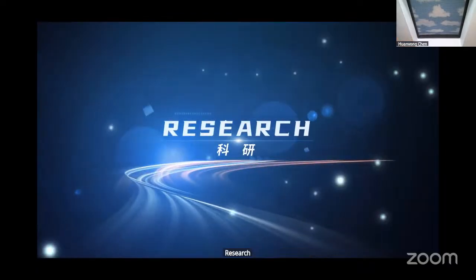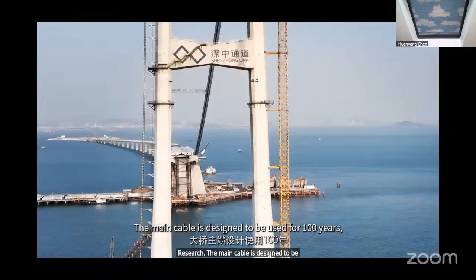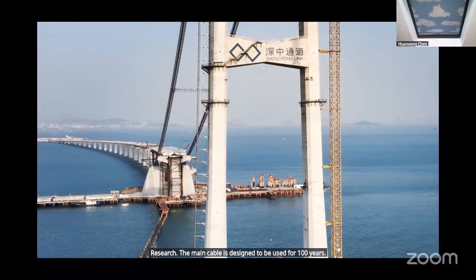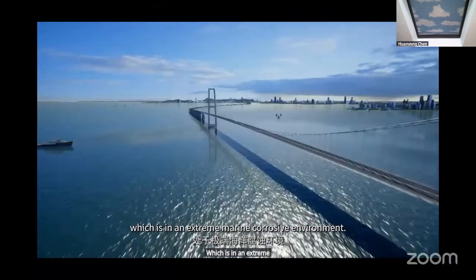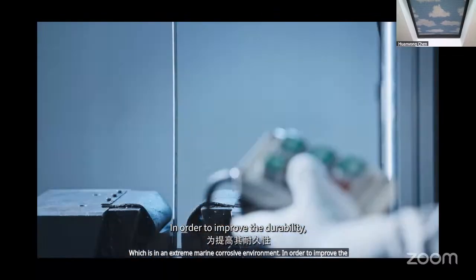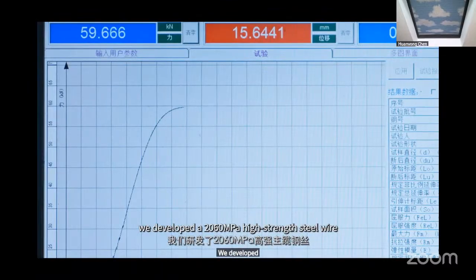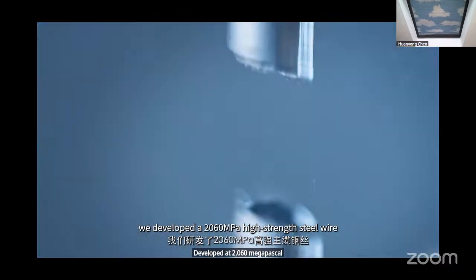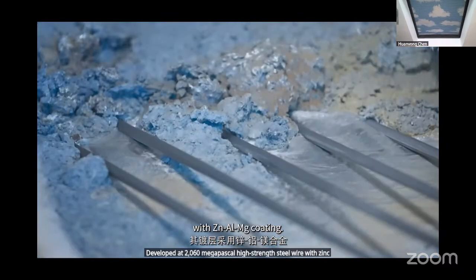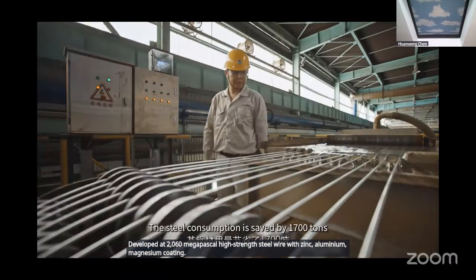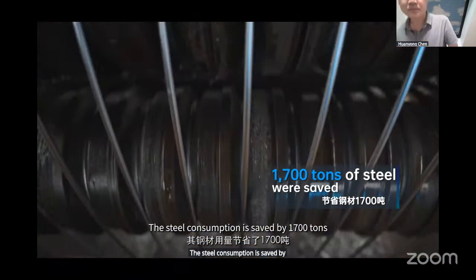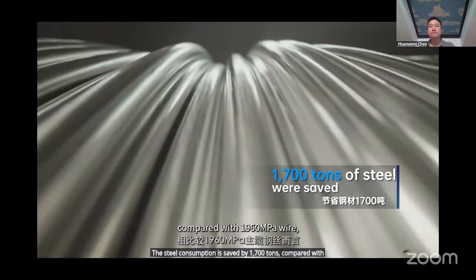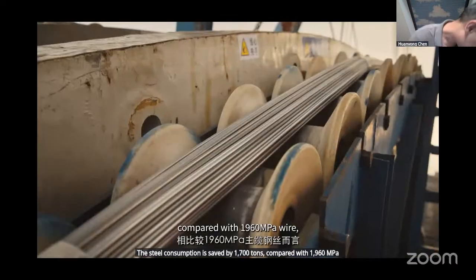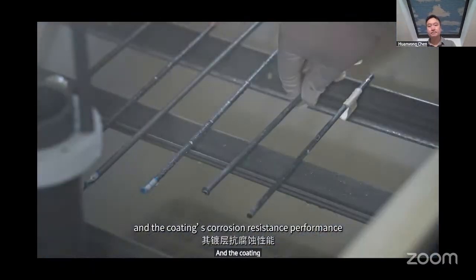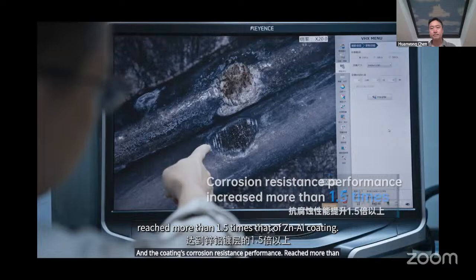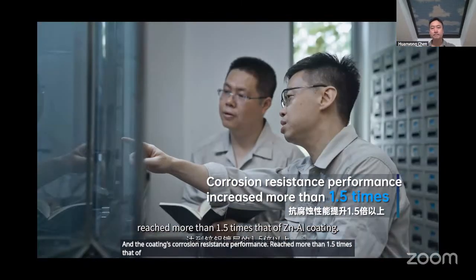Research. The main cable is designed to be used for 100 years, in an extreme marine corrosive environment. In order to improve the durability, we developed a 2060 megapascal high-strength steel wire with zinc aluminium magnesium coating. The steel consumption is saved by 1,700 tons compared with 1,960 megapascal wire, and the coating's corrosion resistance performance reached more than 1.5 times that of zinc aluminium coating.